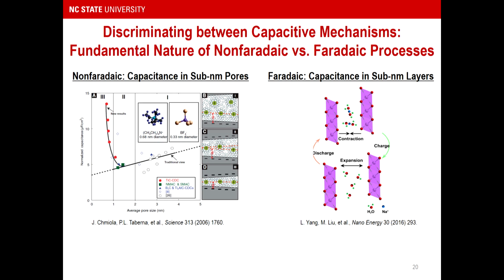The situation looks something like this. When you have these activated carbon materials, they have very, very tiny pores. That's how you get high surface areas. Within these pores, the electric double layer looks quite different than it does at a planar interface. And it's illustrated in this schematic as something that begins to look, at least in my eyes, as something that looks like intercalation. In some cases, you even have the desolvation of these cations taking place.